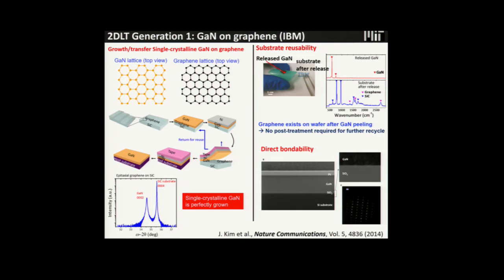Then we took a picture, after peeling off, of the IBM logo. We peeled off the gallium nitride. And also, an important thing is, after you peel off, we found that the graphene is still on the wafer. So then you don't have to re-graphitize the wafer. All right. So when you peel off, it's an atomically flat surface. Graphene on the substrate has about 5 angstrom RMS roughness, a mirror surface. The other side of the peeled-off layer is also atomically flat. That means you can do just a bonding process like Soitec does. Soitec has been monopolizing the SOI for a long time, and the key there is that they have to make a very atomically flat interface. So this idea worked in 2013, and was published in 2014.